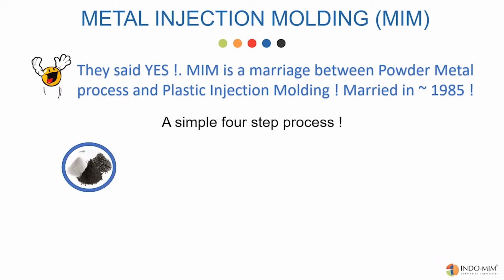Step 1. Mix the metal powders with some binder, usually a mix of polymers and wax. Mixing is done under heat so that the binder material melts and coats each metal particle. This produces a homogeneous mix. The mix is converted into small pellets for easy storage and transfer. At this stage, the mix is called MIM feedstock.